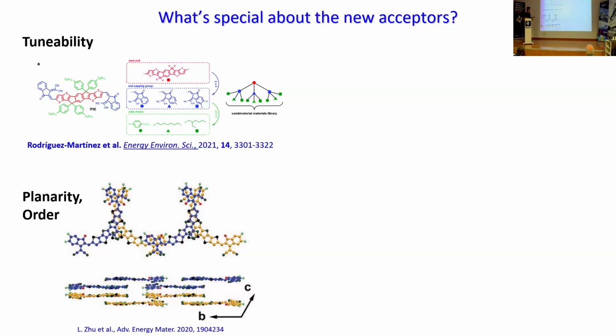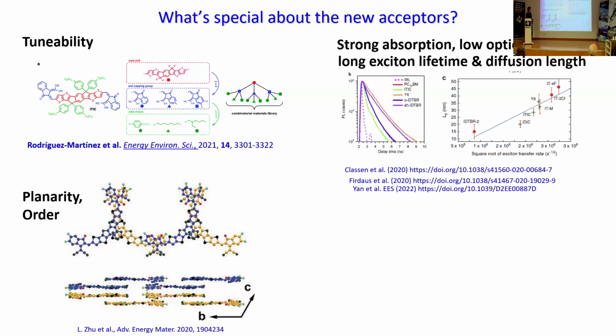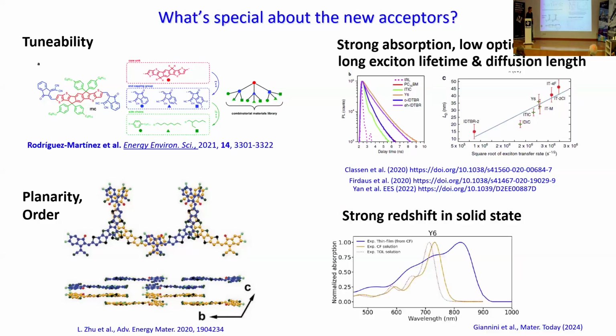So you tend to get reasonably good crystalline structures formed with good pi-pi interactions between neighboring molecules. They tend to have rather favorable excited state properties. So the exciton lifetime might be a nanosecond or so. That would be very favorable compared to typical conjugated polymers. And therefore, they will have long exciton diffusion lengths.